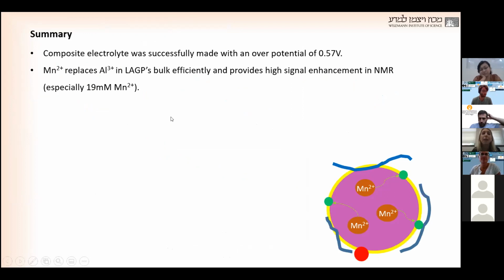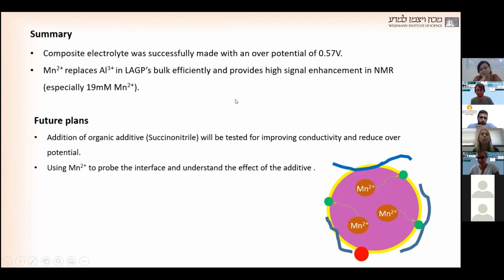So to summarize, the composite that we are making is really successful and has a lower overpotential, and we can replace the aluminum by manganese inside of the LAGP to provide high signal enhancement, especially at 19 millimolar concentration. And the future plan is the addition of an organic additive to lower more the overpotential that we have, and also using the manganese to probe the interface and understand the effect of the additive.